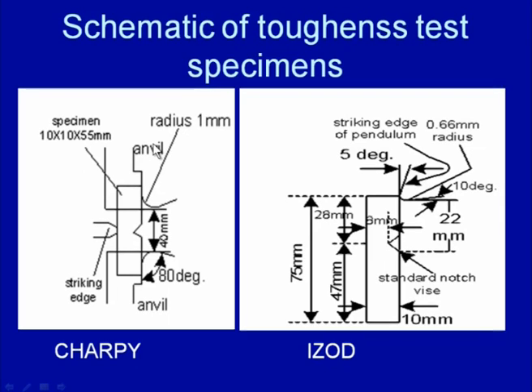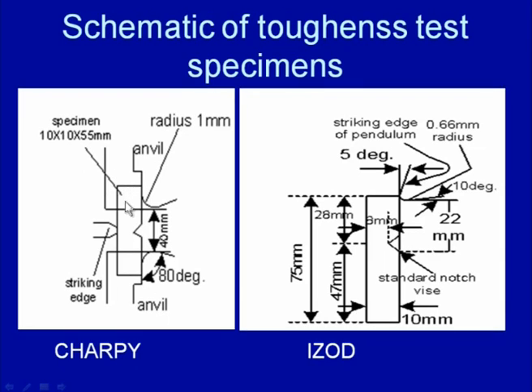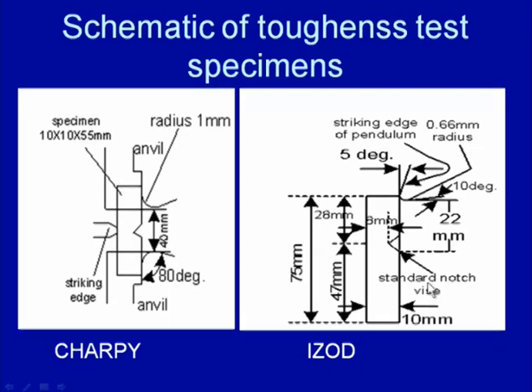To show this, the schematic of the two specimens and their dimensions is shown here. The first shows the Charpy test, where the specimen is placed on the anvil in a simply supported manner, so it gets support from both ends, and the striking edge of the pendulum hits from the back side, and the energy absorbed is recorded. In the Izod test, the specimen is held like a cantilever, and the pendulum hits from the face side of the notch. These are the different dimensions of the specimen commonly used for the Izod test.